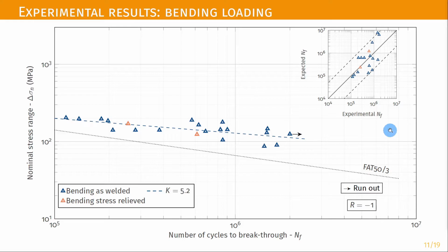Similarly, pure bending tests were carried out. Up to now, it was not found a significant difference between as-welded and stress-relieved specimens regarding the service life. In fact, as can be seen from the expected versus experimental number of cycles to breakthrough, all stress-relieved data, together with the as-welded ones, fall within a factor 5 in the fatigue life range.